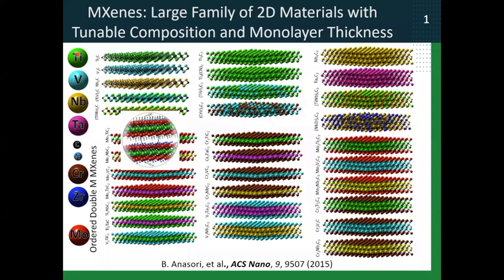Titanium 2C will be 3 atomic layers thick, titanium 3C2 will be 5 atomic layers thick, and now we can produce thicker layers, 5 and 9 atomic thick layers of titanium carbide MXene, and same for other materials. And the last important thing about MXenes that you need to keep in mind is that their surfaces are covered by functional groups. Potentially, these functional groups are also tunable, but it turns out to be not an easy problem to solve.